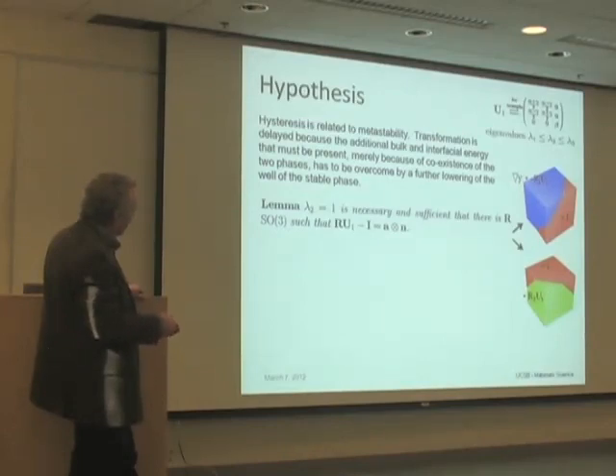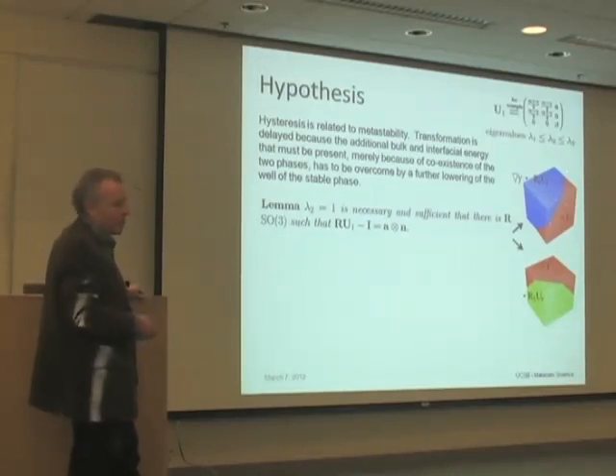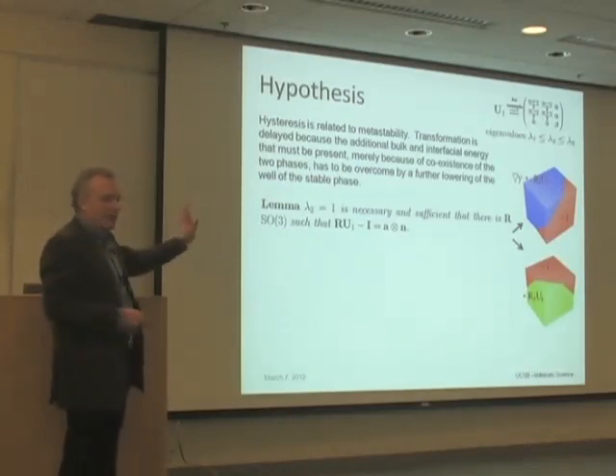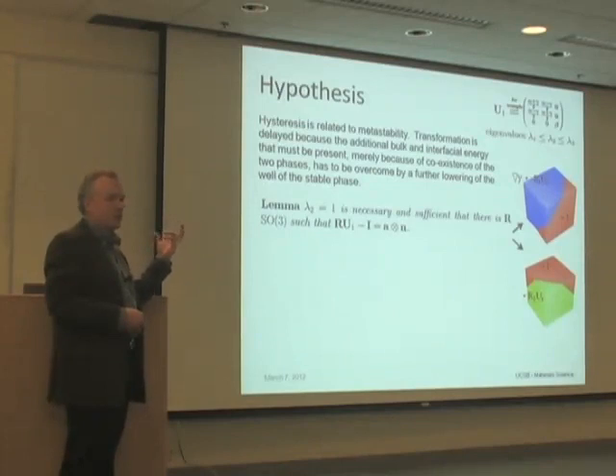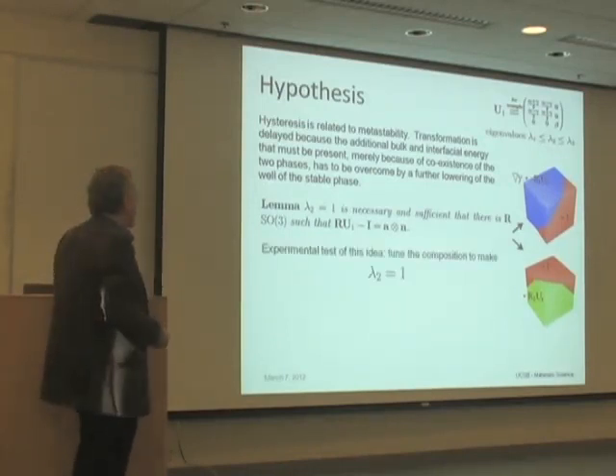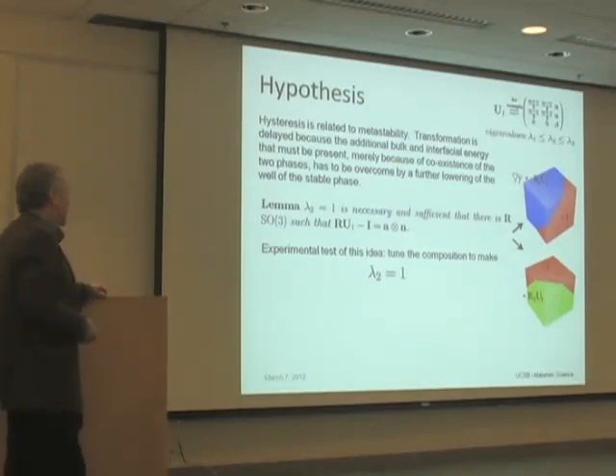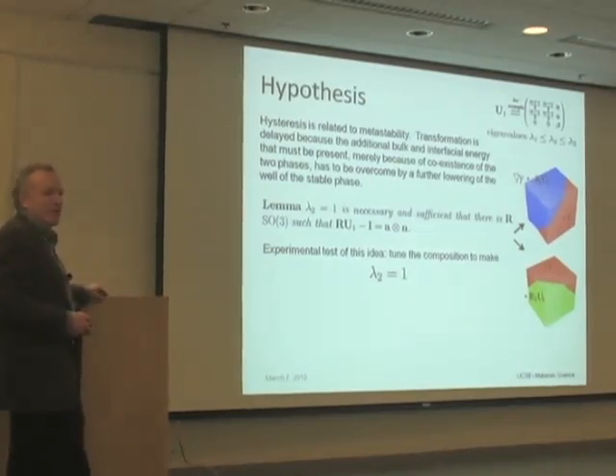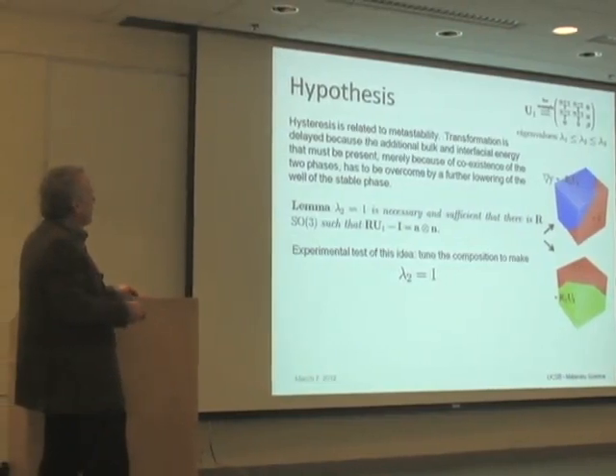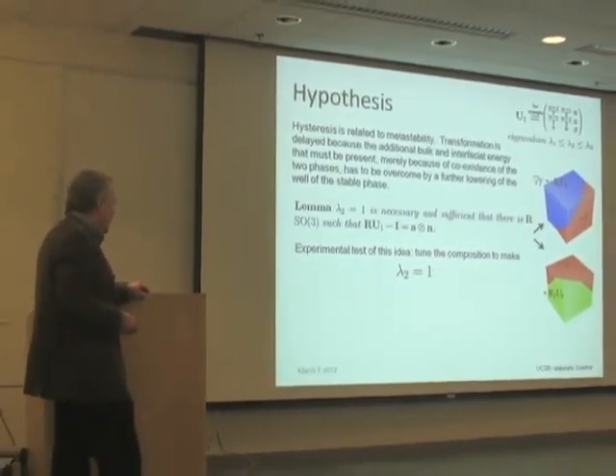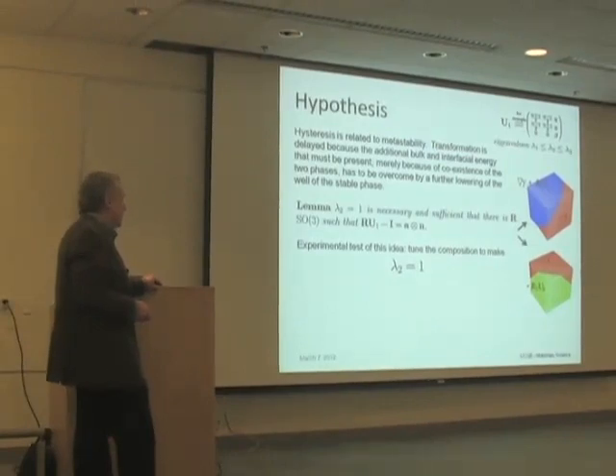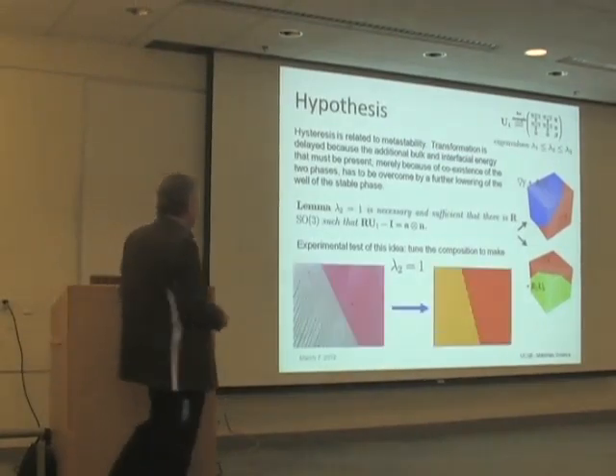They look like this. There's a distortion over here. There's no distortion over here, but they still fit together perfectly on an interface. So I've completely eliminated this elastic transition layer and this interfacial energy. If this is the reason for hysteresis, the size of the hysteresis loop should go down when you do this. So that's the experimental test: tune the composition, because this transformation stretch matrix depends on composition, to make the middle eigenvalue lambda 2 of the transformation stretch matrix 1. And then you should change from those kinds of interfaces to those kinds of interfaces.